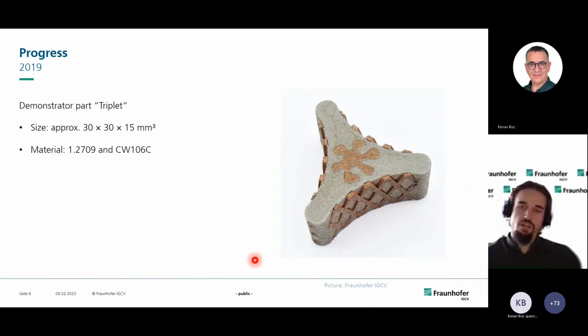So let's head on to a bit of our parts over the last years. This was one of our first multi-material parts. It's called the triplet. It's a very small part, as you can see. It's just 30 by 30 millimeters in the base, and it's made out of a tool steel and copper chrome zirconium. This was made on our SLM250, which only had a build plate, a square with 50 by 50 millimeters length on each side.